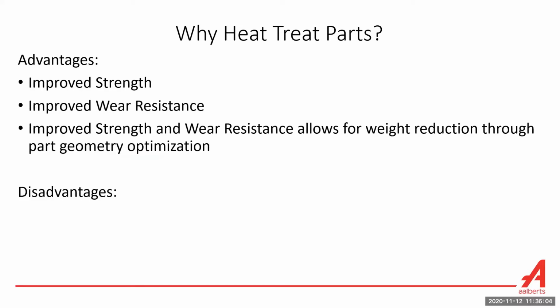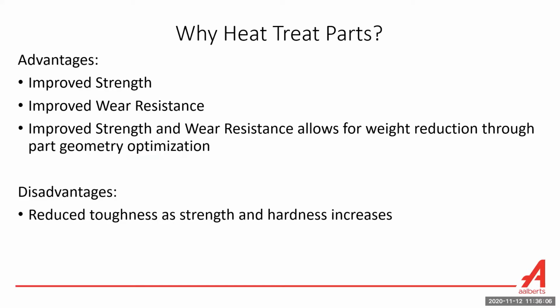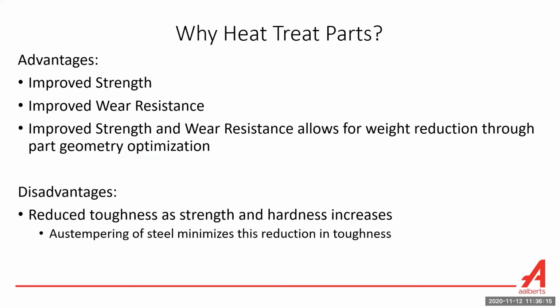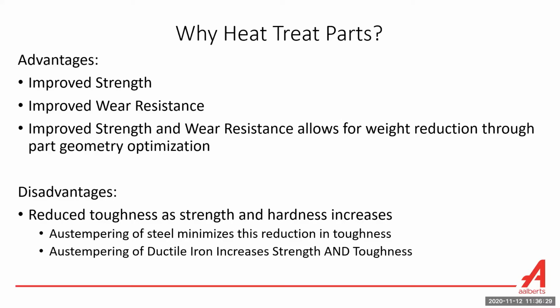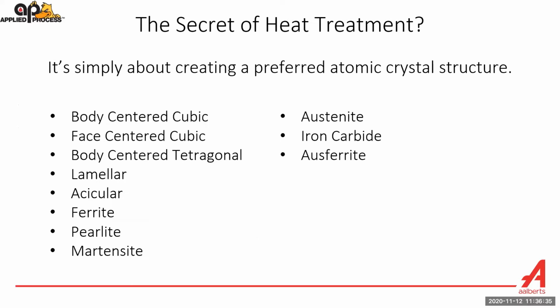The disadvantages of heat treatment is it can reduce the toughness as the strength and hardness of the material increases. Then the interesting thing about molten salt quenching, or Austempering, is it minimizes this reduction in toughness. So it retains a higher level of toughness than if you were to process parts through a traditional heat treatment process. And interestingly enough, we'll talk about Austempered ductile iron. It both increases the strength and the toughness of the material.